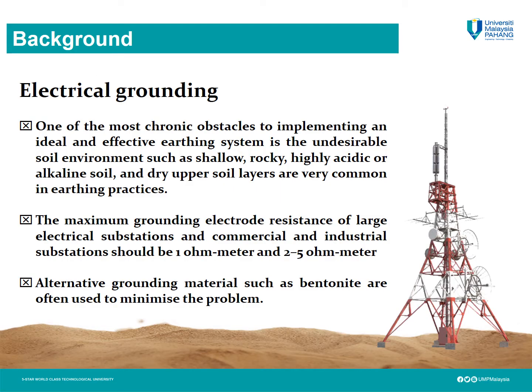As for the background, electrical grounding, one of the most chronic obstacles to implementing an ideal and effective earthing system is the undesirable soil environment, such as shallow, rocky, highly acidic or alkaline soil, and dry upper soil layers, which are very common in earthing practices. The maximum grounding electrode resistance of a large electrical substation and commercial and industrial substation should be approximately 1 ohm and 1 to 5 ohm. In order to achieve this, alternative grounding material such as bentonite is often used to minimize the problem.